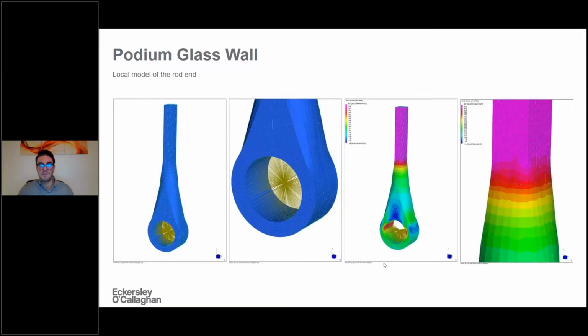In the local model, we had to build and analyze the transition between the rectangular shape of the rod, when it's interfacing with the glass, to this rod end for the pin connection at the bottom and at the top, and to study whether there was any risk of stress concentration in this transition area.